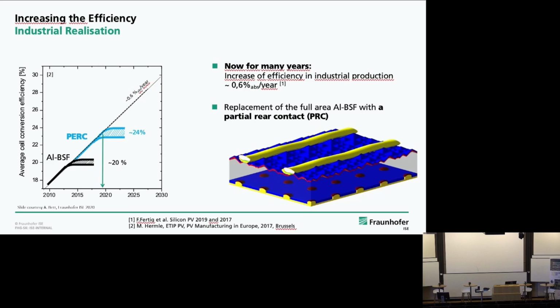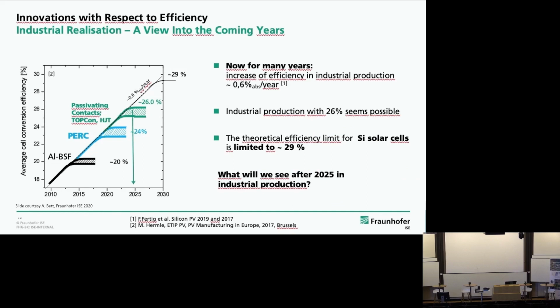99% of the surface is well passivated, and this PERC technology is now the world dominant solar technology, and the glass ceiling of this technology is about 24%. It's already 20% more than the ALBSF technology, and the most interesting factor for the big Chinese manufacturers of this technology was you can convert a standard ALBSF production line to PERC. You just have to exchange a few machines.